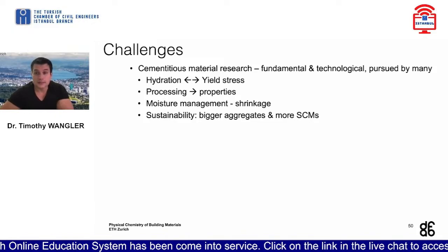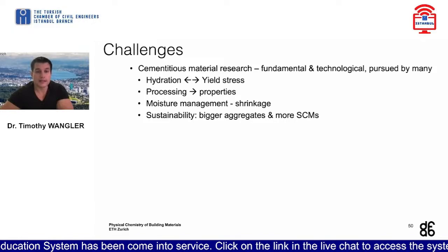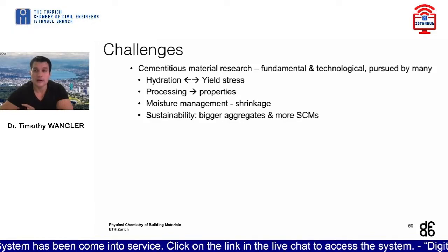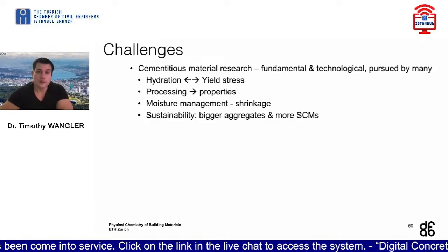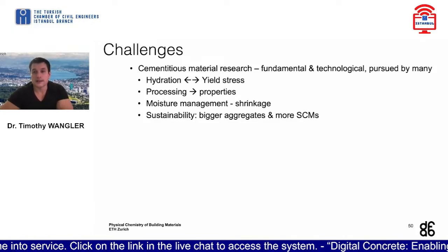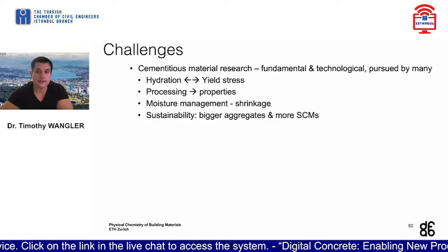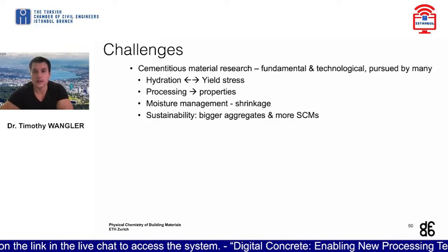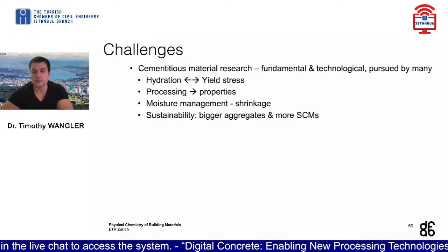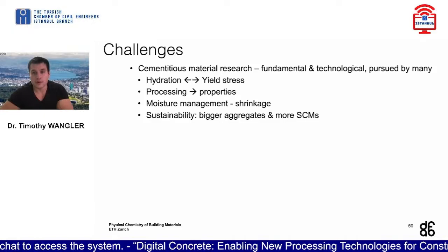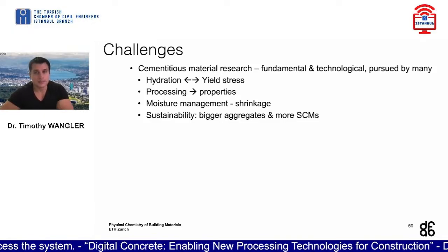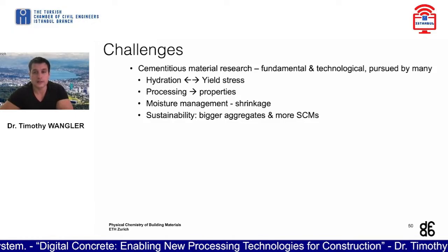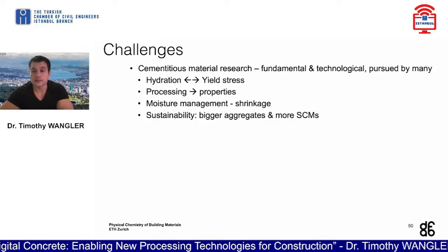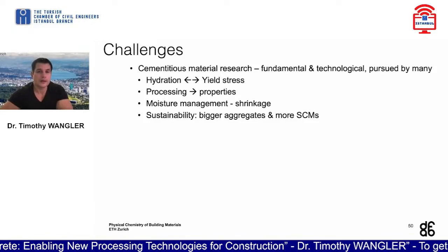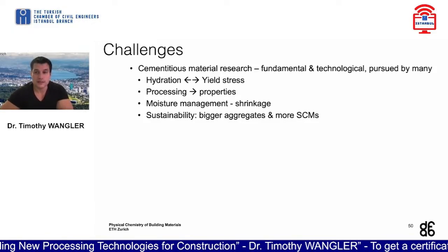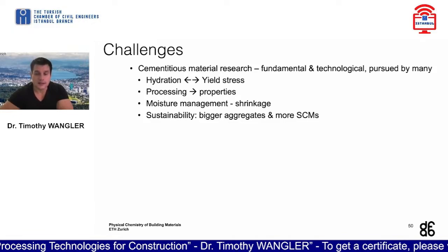Yes, and as I mentioned, sustainability is an issue, and sustainability related to the higher paste contents and higher clinker contents in your concretes. So to reduce paste, you can just use big aggregates and improve your mix design. Until now, coarse aggregates are not used generally in digital fabrication with concrete. Most mixes are with maximum grain sizes of 4 millimeters or less. So the inclusion of coarse aggregates, I think, is a major step that can be taken. There's a couple of 3D printing companies and demonstrations that are already doing it, but it needs to be integrated more into more technologies, especially with acceleration. And then, of course, the introduction of more supplementary cementitious materials to reduce overall clinker content. This is also being researched by many.